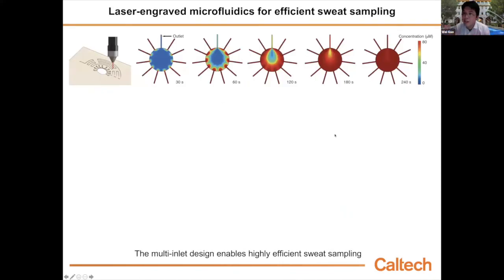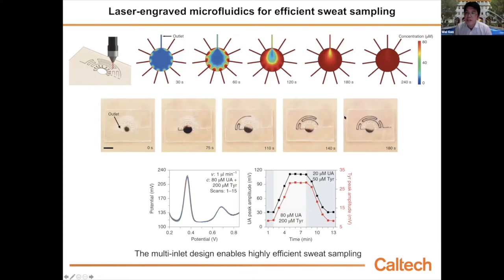For the microfluidic part, based on simulation, we see they can sample the sweat very efficiently. When the new sweat comes out, it pushes away the old sweat. It takes 2 to 3 minutes to fully refresh the old sweat. That means there will be a delay of roughly 2 minutes, but we think 2 minutes is pretty short for continuous wearable molecule sensing. We see how sweat comes out, enters the microfluidics, then flows out from the outlet.